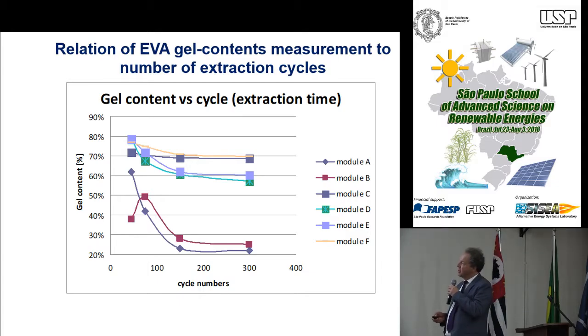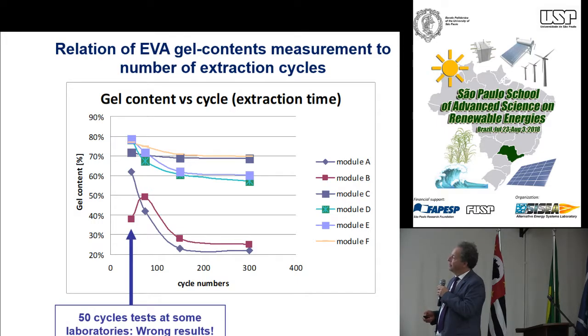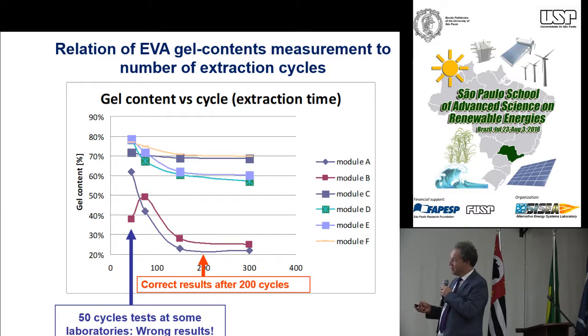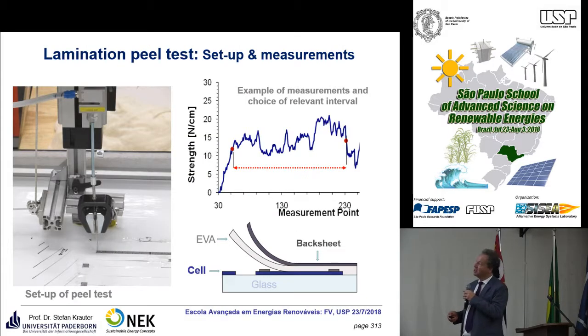If you do the gel content test of the state of polymerization, it depends on the number of cycles. We compared some laboratories, and some of them, in order to save time, do not wait until the result stabilizes. They do it before, and sometimes it appears to be 50% polymerized, but in the end you find out it is only 20% polymerized if you wait for the end results. The correct result only occurs after 200 cycles. So if you choose a testing laboratory, make sure that they do 200 cycles to really get the correct results.